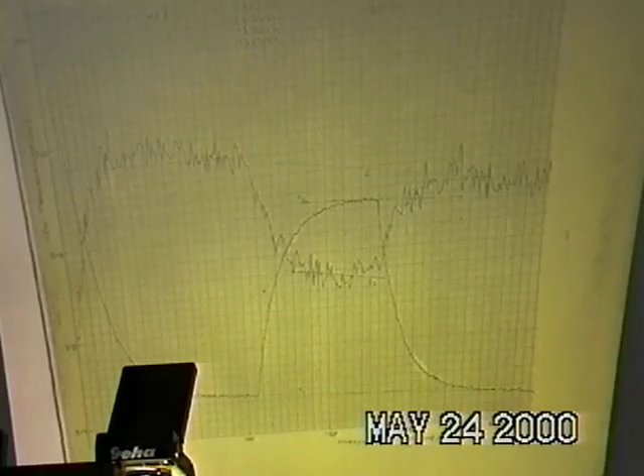Again, when the temperature goes up, the cell voltage goes down, but it comes back to about the same baseline. You can see you need to average the cell voltage because of the fluctuations it goes through. You have to use an average value for cell voltage. I plotted this out point by point on large chart paper. This is rather tedious. It takes maybe 2 hours to plot a data point like this, but it's a good exercise to test what's going on in your system.